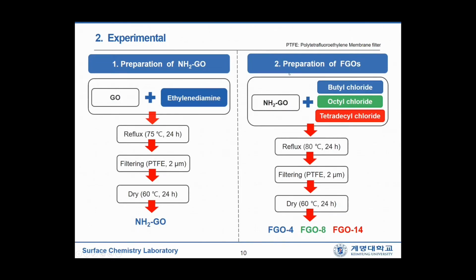The second step is the alkylation of aminized graphene oxide. Aminized graphene oxide is mixed with 3 kinds of alkyl chloride, which are butyl chloride, octyl chloride, and tetradecyl chloride, etc. These mixtures are refluxed at 80 degrees for 24 hours and filtered by PTFE filter with 2 microns of pore size, and then dried out at 60 degrees for 24 hours.